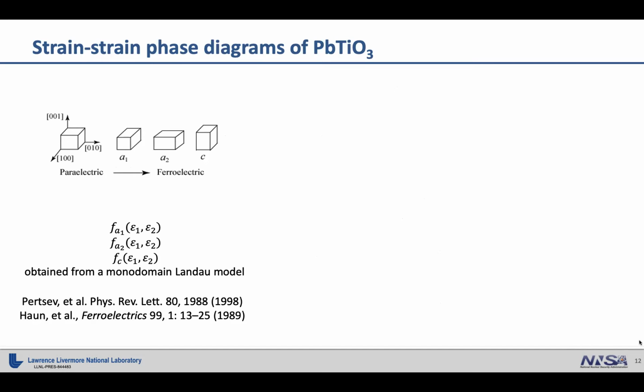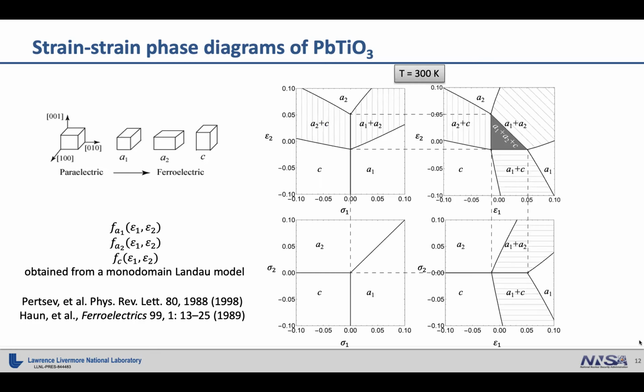The first case is lead titanate, and we consider the tetragonal phase, which has 3 domain variants in the 001 orientation. And the input we need is just a mono-domain Landau model from the earlier paper, with the coefficients also from the Landau free energy 6th-order expansion. So we can construct this strain phase diagram and stress phase diagram for a given temperature of the 001 oriented lead titanate. And what's more interesting is that due to the dual relationship which I showed between the strain and stress phase diagrams, there's a nice correspondence between the strain and stress phase diagram just by performing the Legendre transformation, which means if you know the strain phase diagram, you can construct the stress phase diagram and vice versa.